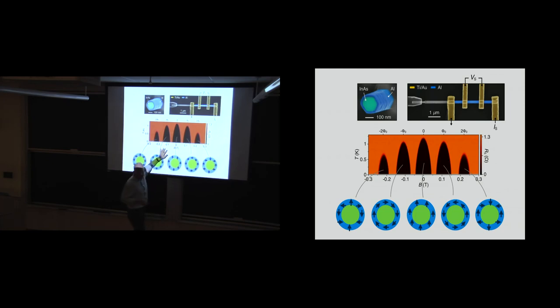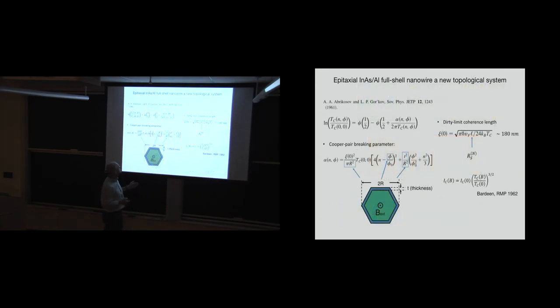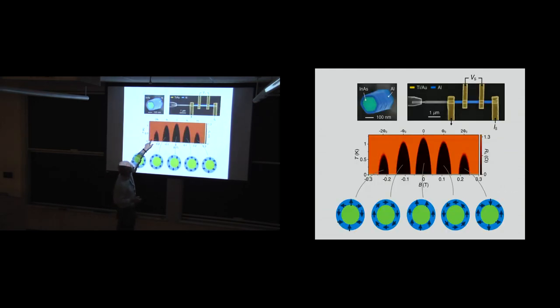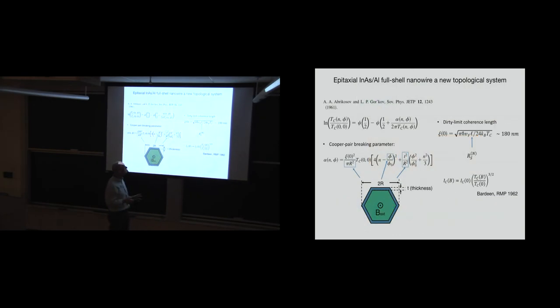But we measure the gap, and so we can just figure what that is from BCS, so it's not even adjustable, but you can just take that number from the top, that's okay. And then one other thing, which is the coherence length. But the coherence length just depends on the resistance of the wire. The coherence length is just given by that orange color. So we know the orange color is 1.3 ohms or something like that. We know the thickness and we know the diameter, so we know what the mean free path is, and that gives the coherence length as a function of TC.